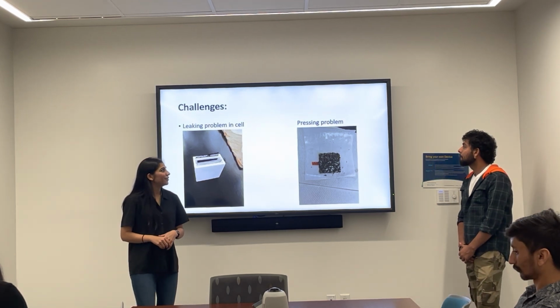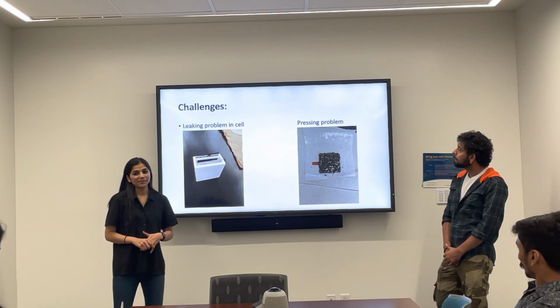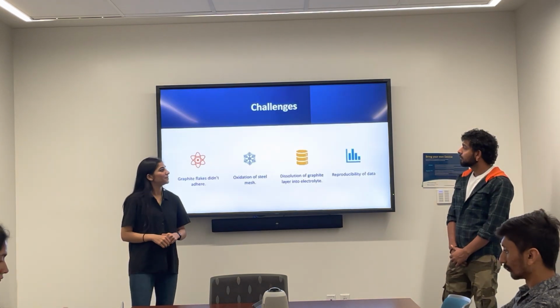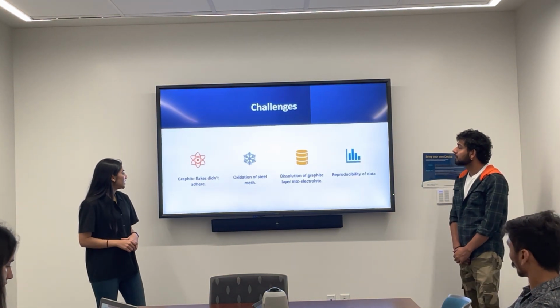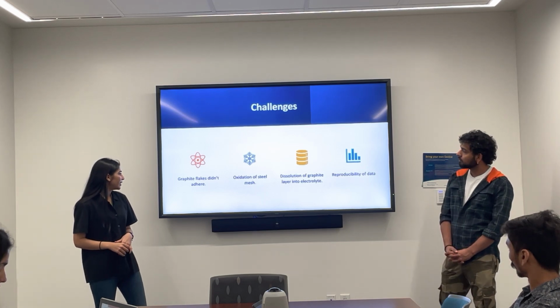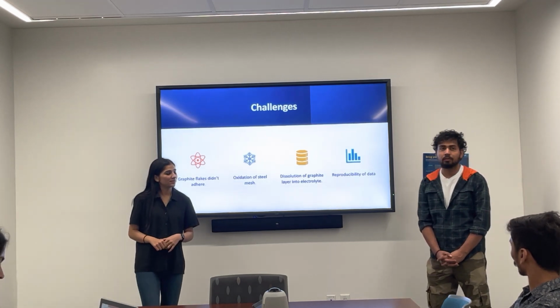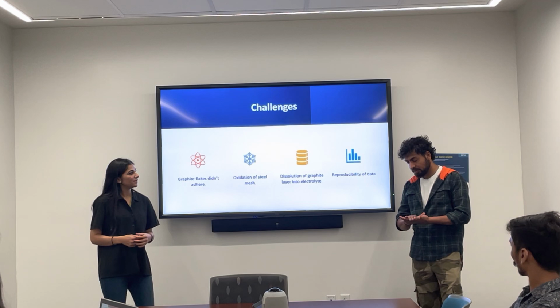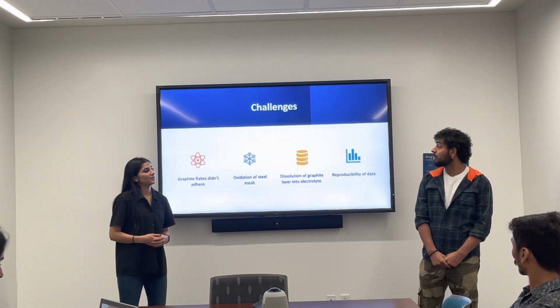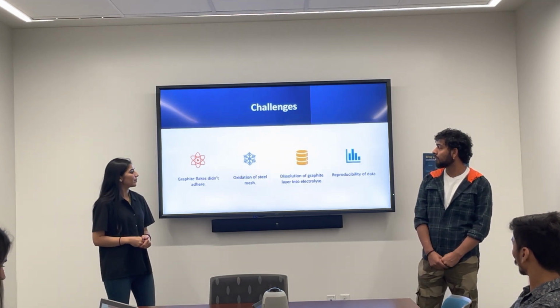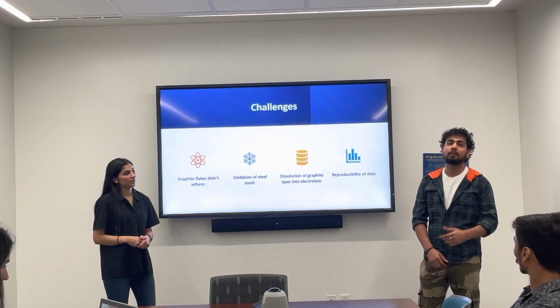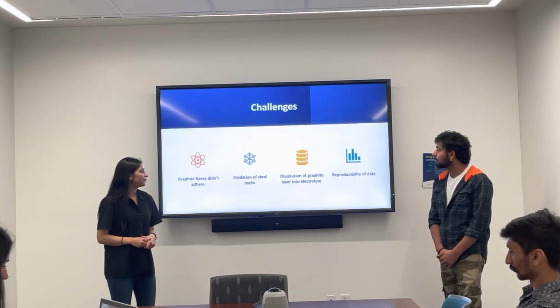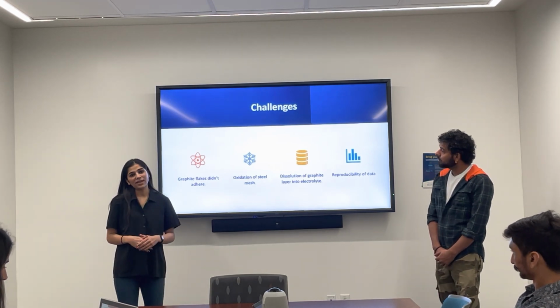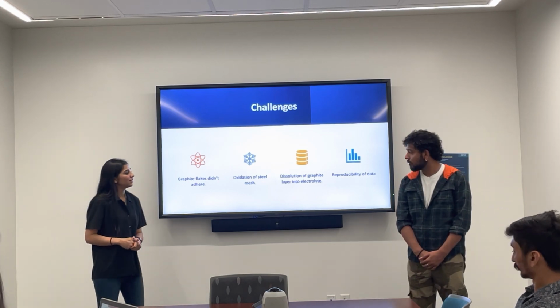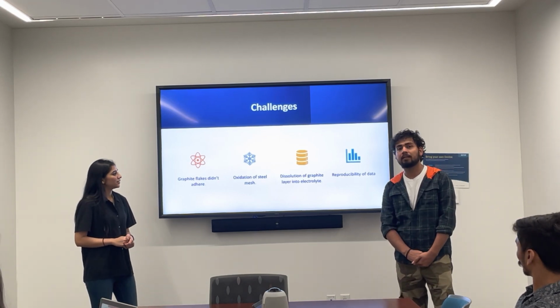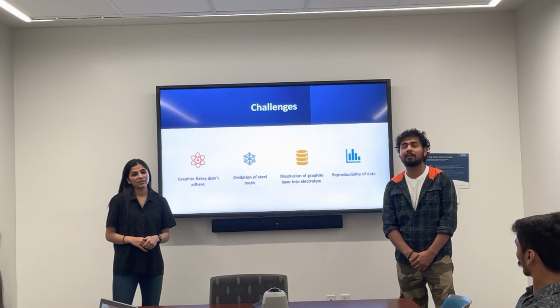Then we faced the pressing problem. The first issue was that the graphite flakes didn't adhere. To make a mesh, we have to make a slurry, and flakes didn't work well for us, so we used graphite powder. Then we faced oxidation of the steel mesh. That's because of overheating, so we reduced the time in the furnace. Earlier it was 1 hour, now it is 45 minutes.